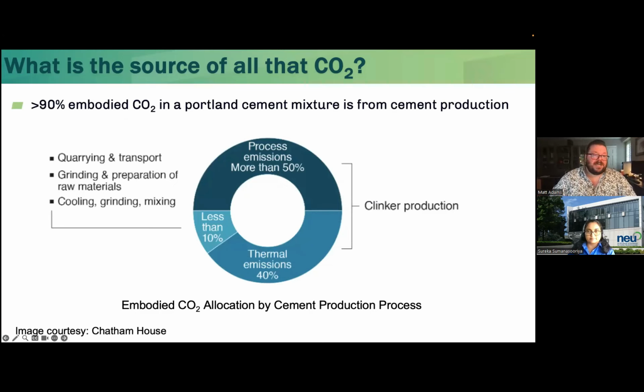And this can be broken down into the quarrying, transport, and grinding processes, the process emissions, which are chemical emissions that come from the process of making the cement, and then thermal emissions, which are really associated with burning the fuel to heat up the kiln for making cement. So you can see from this graph from Chatham House that more than 50% of the total CO2 that we're producing when we make cement is coming from that chemical process. So at the moment, it's not really avoidable.